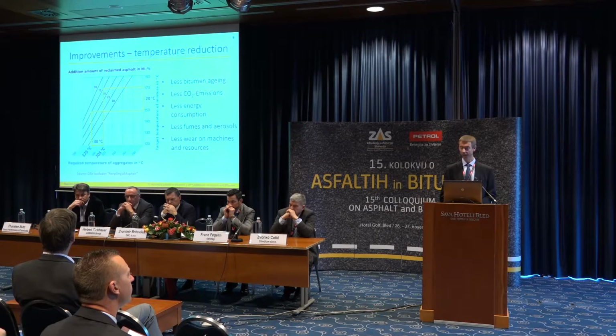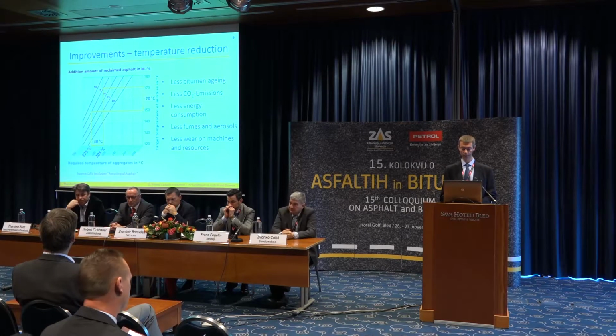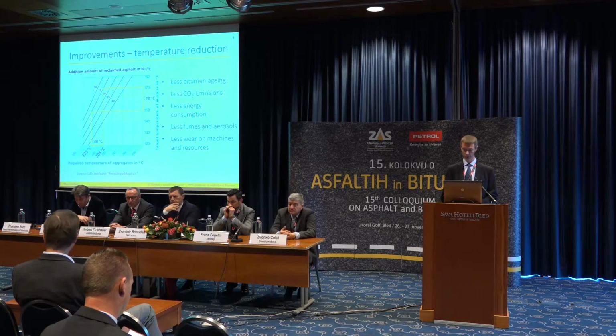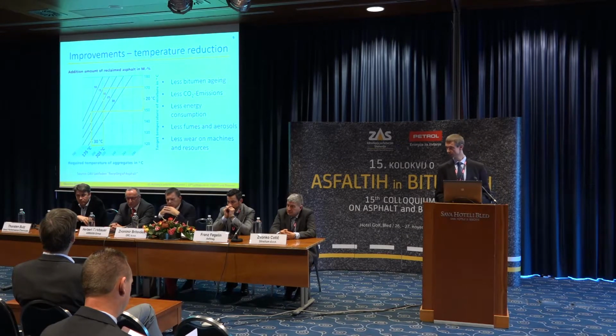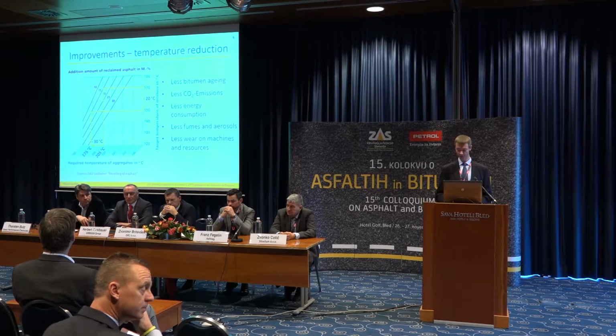We have less aging of the binder in the RAP, and of course also of the fresh, newly added binder. The carbon dioxide emissions are reduced, and also the bitumen fume and aerosol emissions. The energy consumption at the mixing plant is lower, and we also have some reduced wear and tear on the machines in the mixing plant.